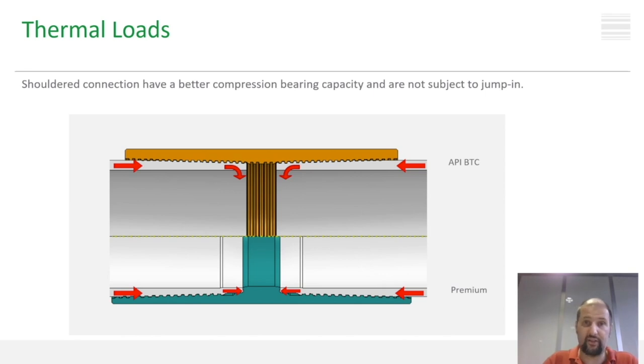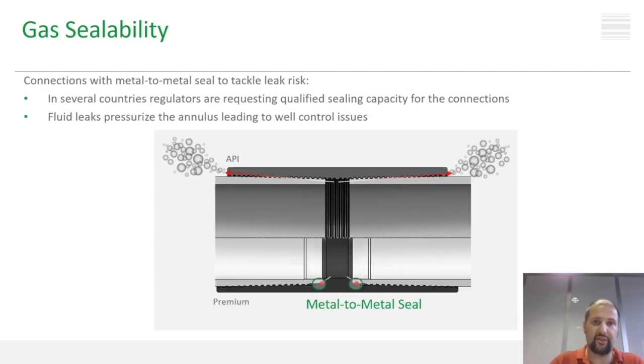On the other side, shouldered premium connections bear compression also in the pin nose and box shoulder, minimizing the risk of a jump-in. Another advantage of premium connections is gas tightness, given that these connections have a metal-to-metal seal. Metal-to-metal seals are designed with a geometric interference that, when made up, generates a contact pressure between the pin and the box, which is engineered to avoid gas passage. In a buttress connection, there is no metal-to-metal seal, so no barrier for gas migrating from the inside of the production casing to the annulus.